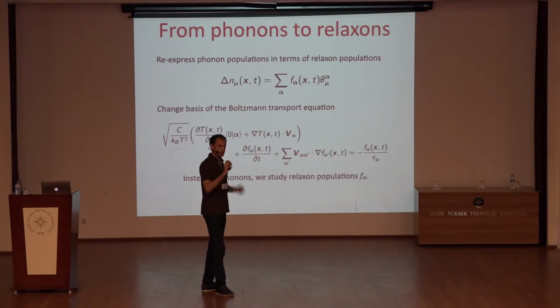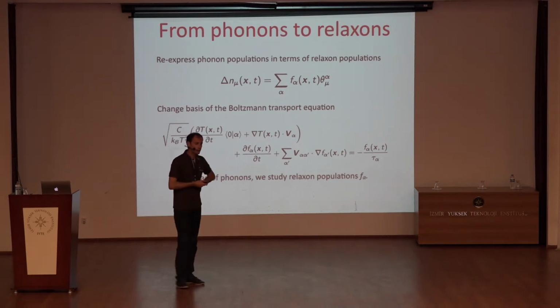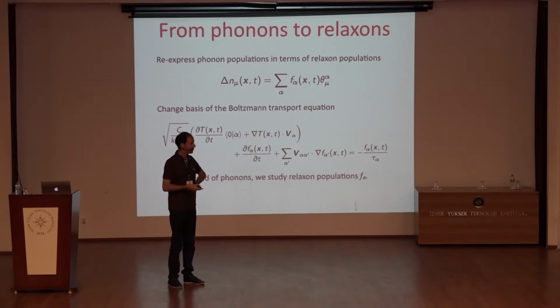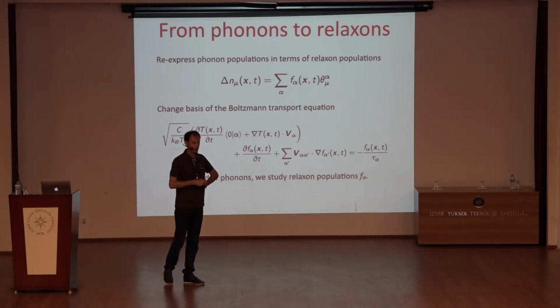The assumption is that the Boltzmann transport equation holds. That's the only assumption, because then you can prove that diagonalization is always possible, due to the fact that the scattering matrix can be shown to be symmetric and positive definite, and that mathematically ensures that you can always find a set of eigenvalues and eigenvectors.